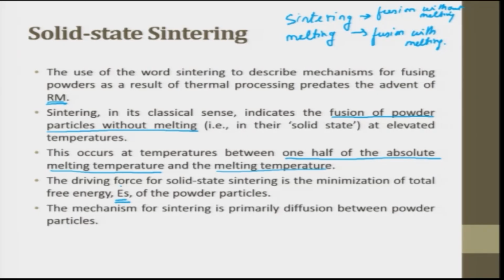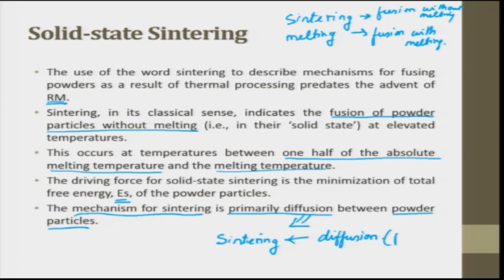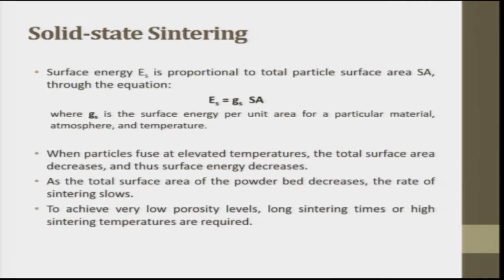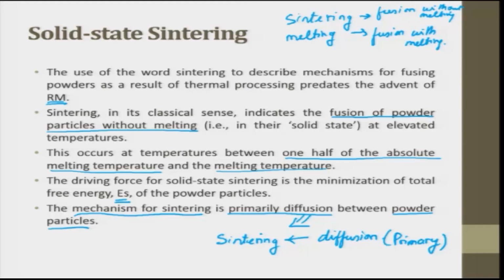So, the driving force which drives solid state sintering is the minimization of the total free energy of the powder particles. The mechanism for sintering is primarily diffusion between powder particles. So, this is very, very important. Sintering process, the primary mechanism is diffusion. You have many more, but this is the primary mechanism.